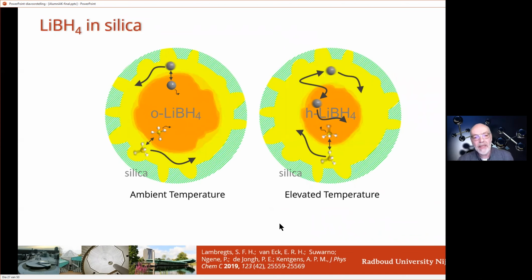And that brings us to the complete picture, well, more or less complete. So suppose the green striped area here is the silica pore. It's corrugated, and the lithium boron hydride gets infiltrated into this pore. And what we now have as a model, which fits all our data, is that in the center of the pore, you get a rigid fraction, which is the regular bulk matter. But around it, the lithium boron hydride cannot, say, crystallize. And it remains fluid. And that means that both the BH4 units and the lithium units freely move through this shell, whereas at low temperature, inside this solid core, hardly anything happens.